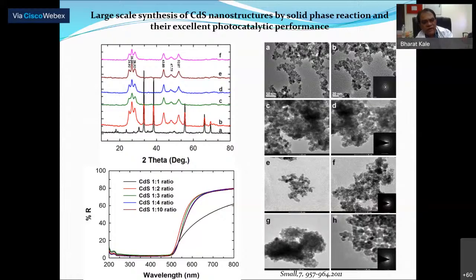So for this, we required nanoscale materials in huge quantities. This is one of the processes we developed: very small size cadmium sulfide in large quantities. We can have 5 nanometers of cadmium sulfide in large quantities, maybe a 500 gram or 1 kg batch.